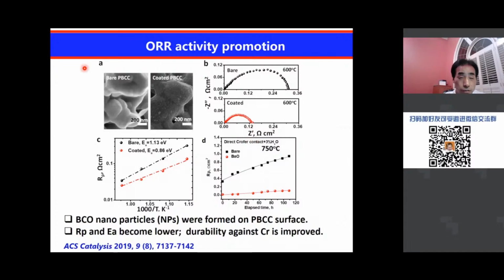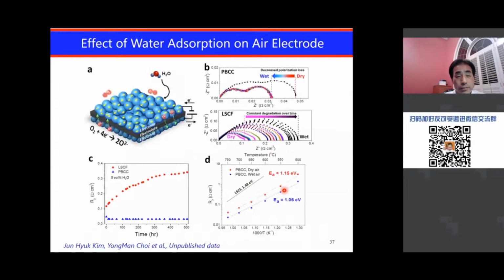So here is just an electrochemical measurement in comparison to a bare PBCC electrode, and with the coating of nanoparticles, the resistance is dramatically reduced, and also the stability is dramatically increased.